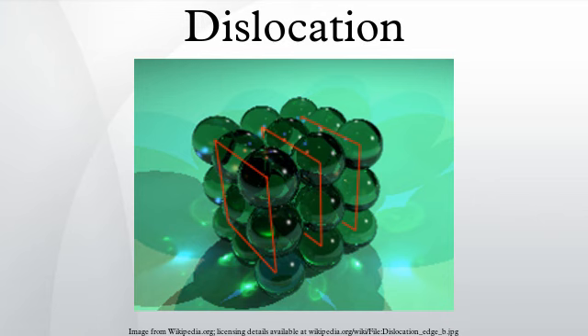Observation of dislocations. When a dislocation line intersects the surface of a metallic material, the associated strain field locally increases the relative susceptibility of the material to acidic etching and an etch pit of regular geometrical format results. If the material is strained and repeatedly re-etched, a series of etch pits can be produced which effectively trace the movement of the dislocation in question.